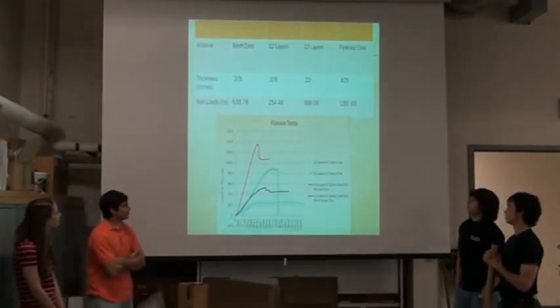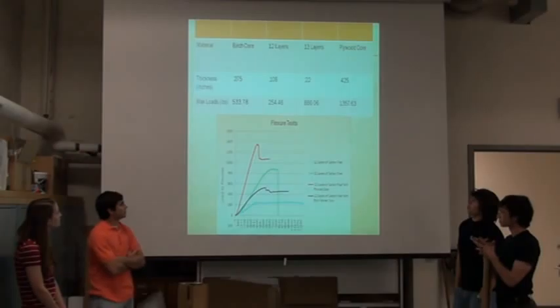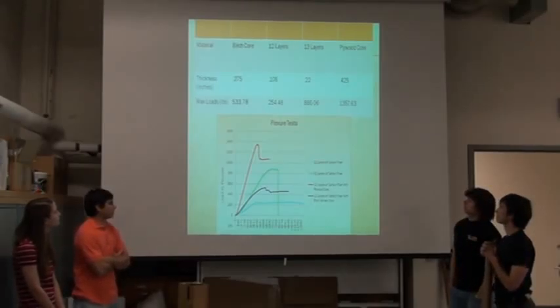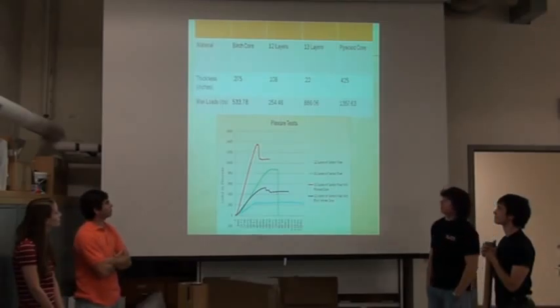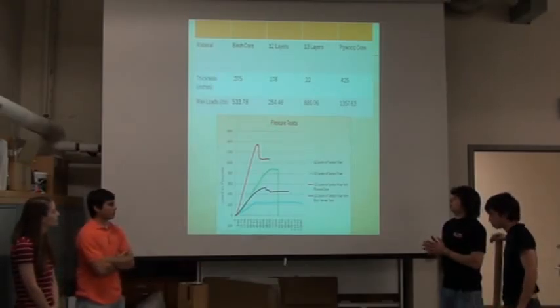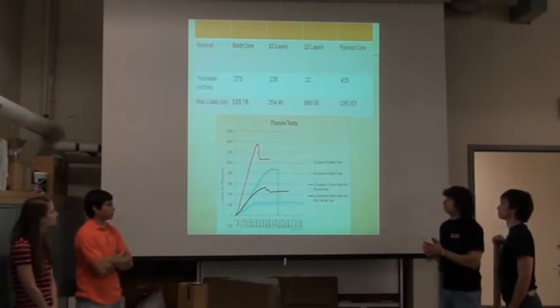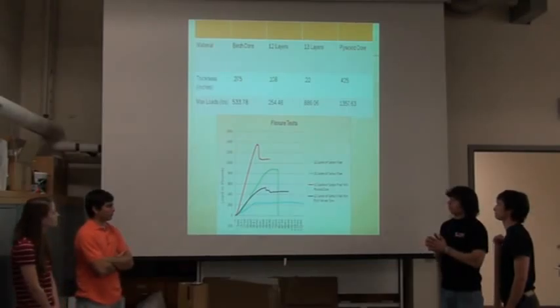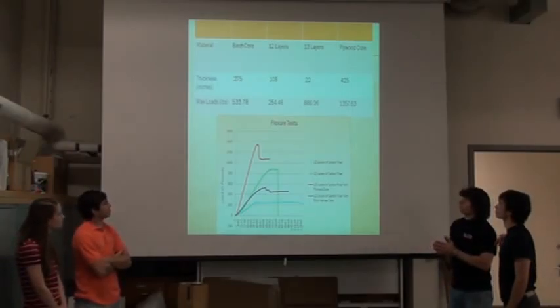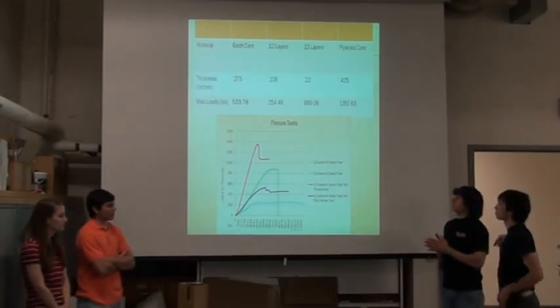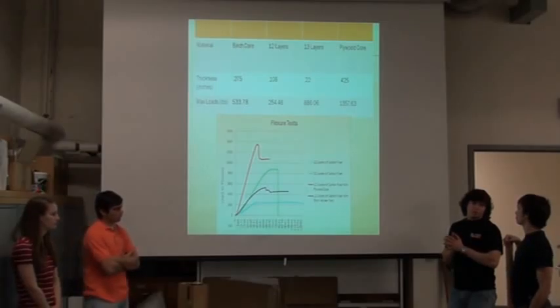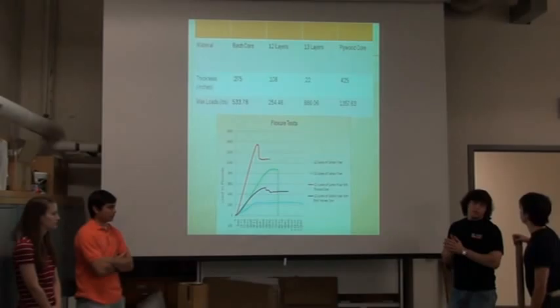So, here are the results of our Flexure tests. We have the birch core and 12-layer and 13-layer and plywood. And they turned out to be different thicknesses when we layered them. And the one that we chose to do was the birch veneer core. And the thickness for the flexure test was .275 inches. And its max load was 533.78 pounds. And the plywood core was stronger because it was thicker.